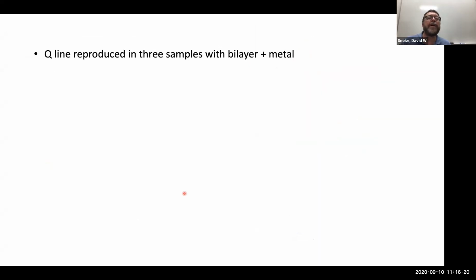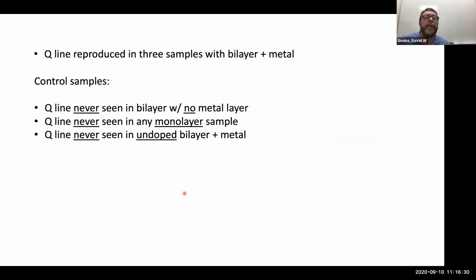All right, so here's a summary of many experiments, many structures that were made. We reproduced this 3 times with 3 different samples. We did control samples. For instance, we made the bilayer without the metal. So everything exactly the same, but not the metal. We never see the Q line in that case, although we see the trion line. We never see the Q line in any monolayer sample.